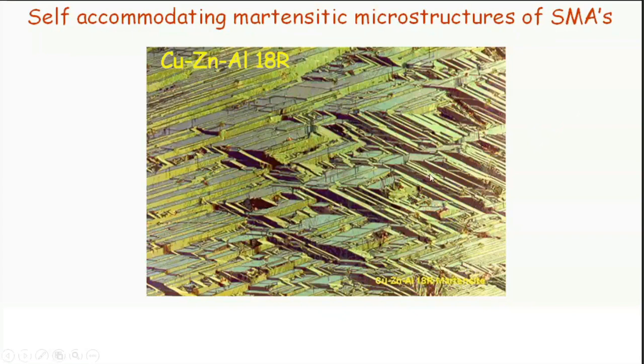Okay, to come back to this, the one thing that stands out in this microstructure is this kind of feature where these martensite variants come together. This is referred to as self-accommodation, and that's because each of these martensite variants in isolation has a shear, and when put all together in a group, their shears cancel each other. The purpose of this is that if an isolated group nucleates in the austenite grain, then there would be a stress field around it, and that acts against the nucleation.